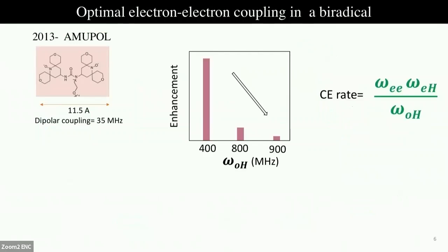AMUPol, we all are aware of, is a gold standard radical, especially at 400 megahertz DNP. But if we see its performance at higher magnetic field, the performance dramatically decreases. This is attributed to the cross effect rate, which is scaled down by the Larmor frequency of the nucleus, say proton here. So if we want to have better cross effect at higher magnetic field, the solution can come from this rate itself: we should increase the coupling such that the cross effect rate remains high even at higher magnetic field.